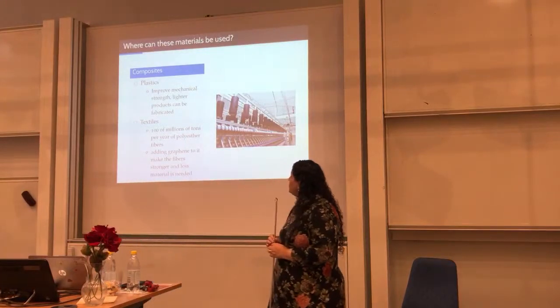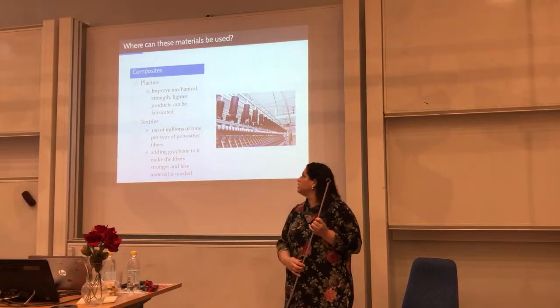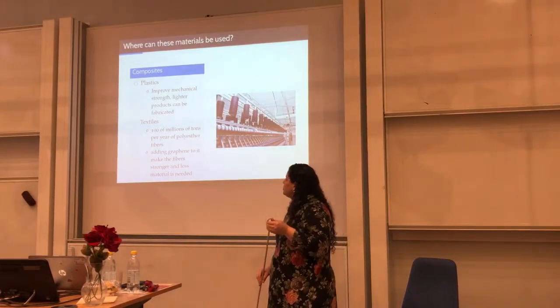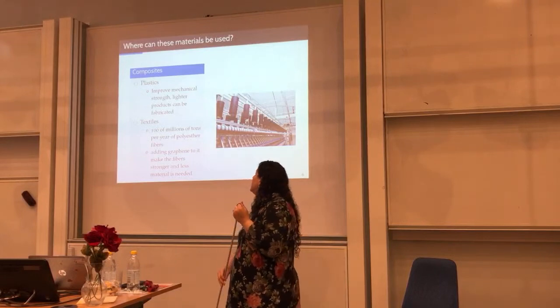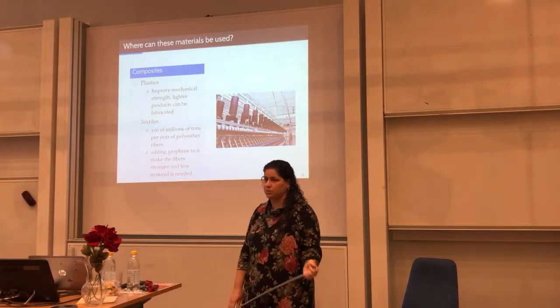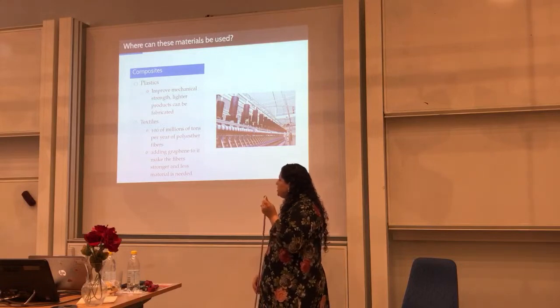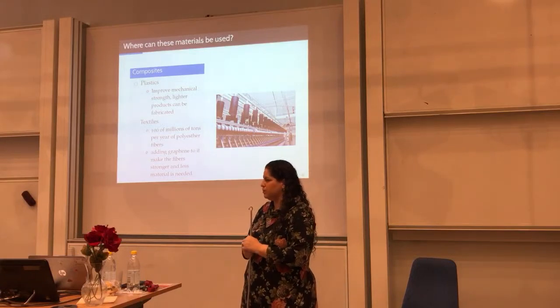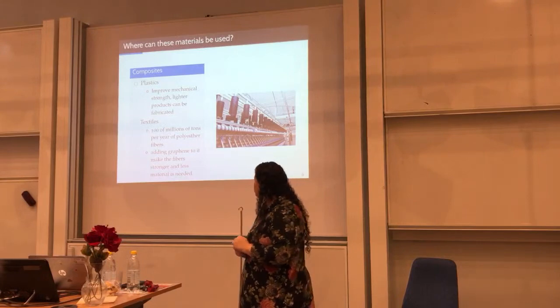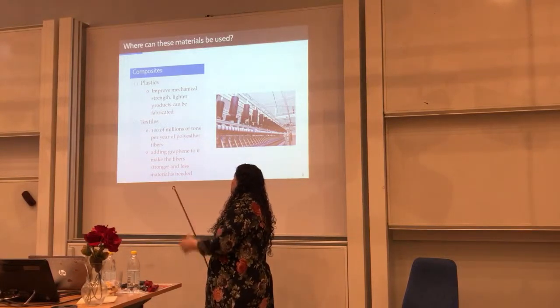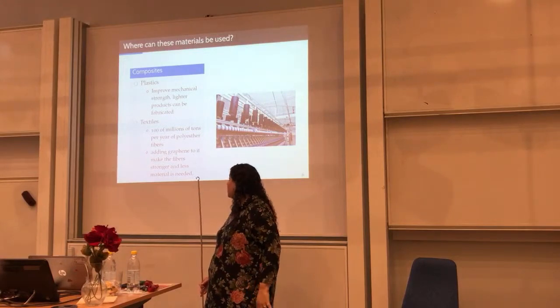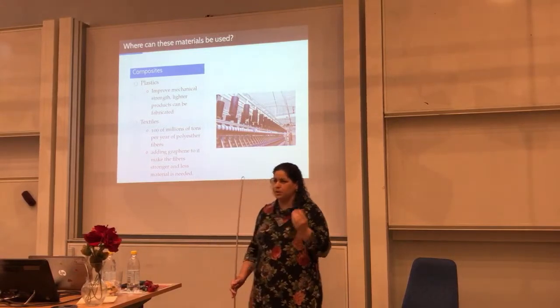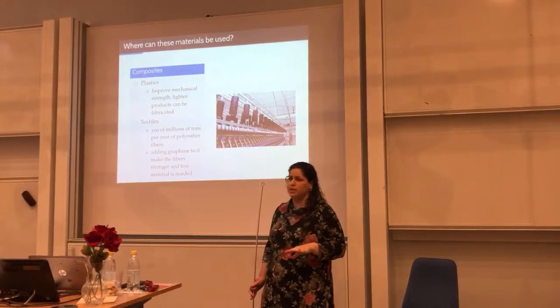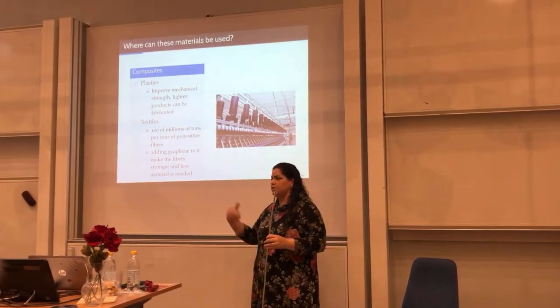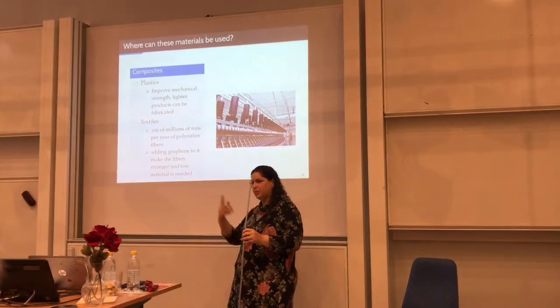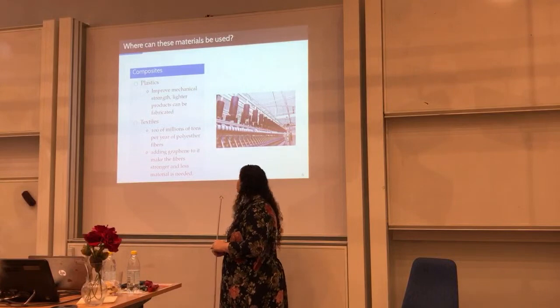We've done the dispersions. And what can we do with it? One of the biggest uses for this dispersion, especially graphene, is to improve the mechanical strength of plastics. So if you add just 0.5 weight percent graphene to a polymer, you can improve the strength by two times, which means that if you're using this polymer or this plastic in a car, you're reducing the weight of the car. If you're reducing the weight, you reduce fuel consumption, so it's just going in a loop, like you are improving the environment in this way.